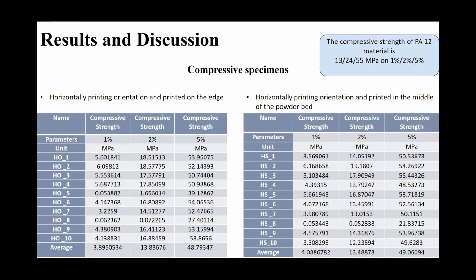In both types of these specimens, there are large deviations in the compressive strength in relation to the values of the compressive strength of the PA12 material itself. The closest values were obtained at 5% deformation. These values are around 50 megapascals, while for material PA12, this value is 55 megapascals.